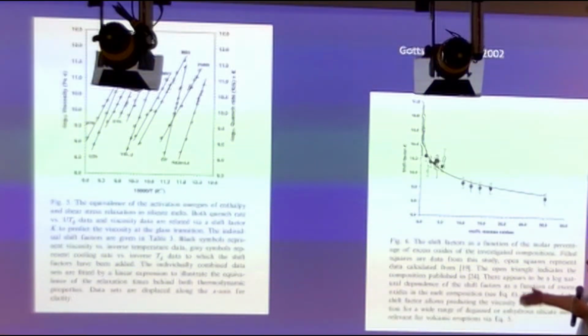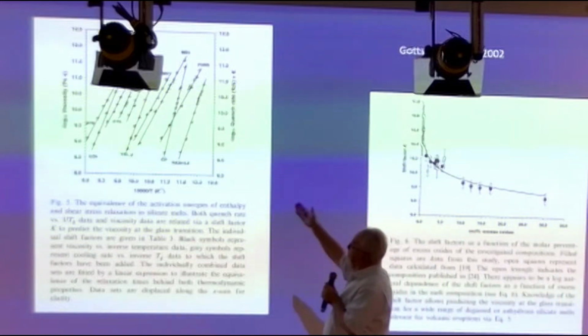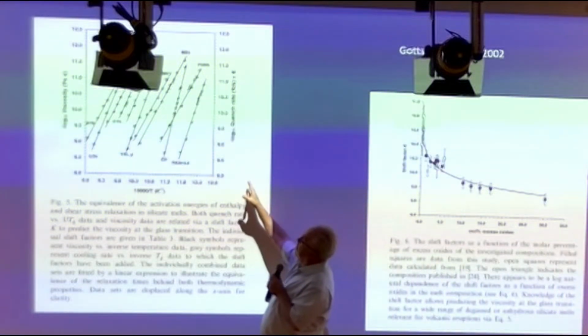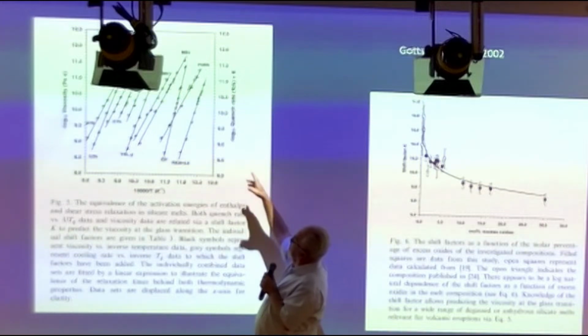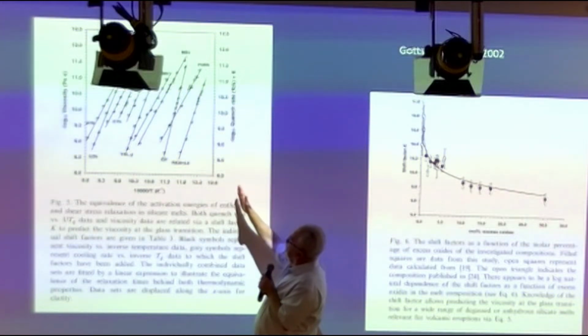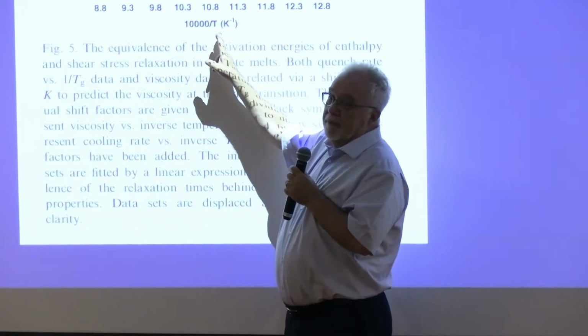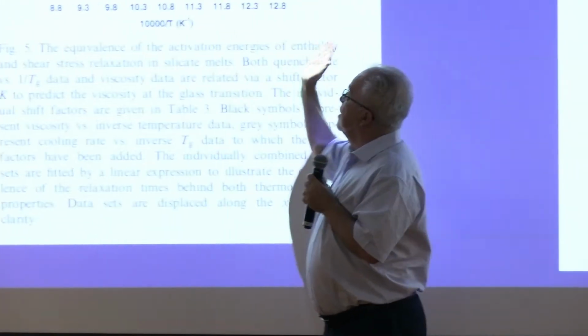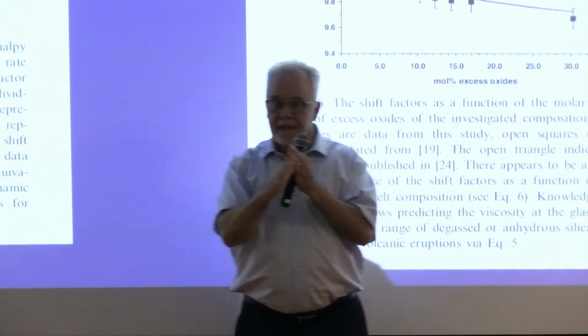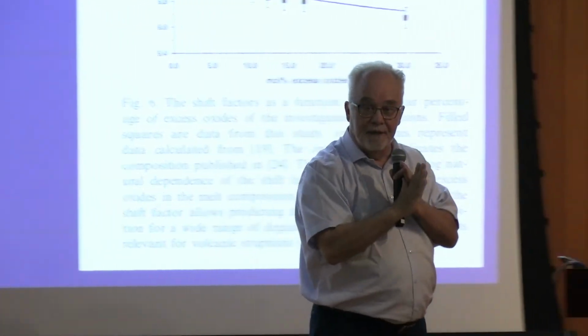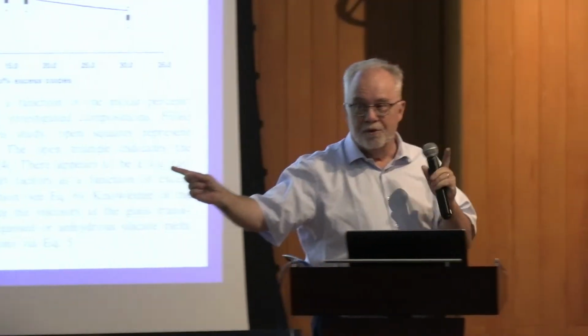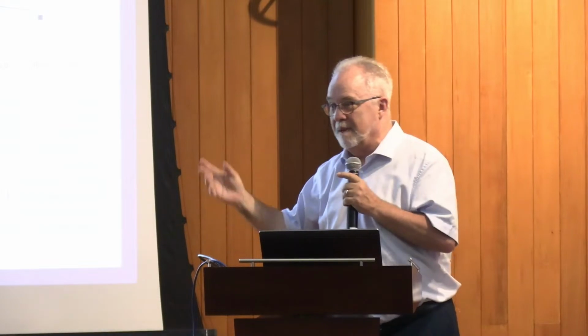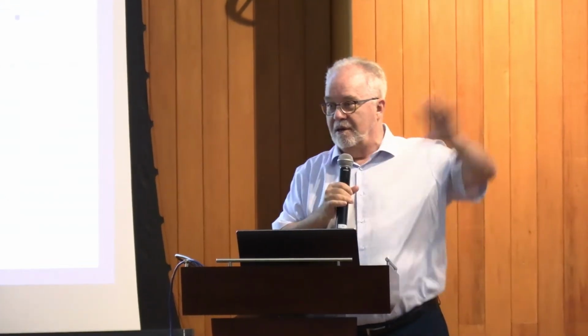And there you have them brought together. You have the two plots together, right? So you have the log of the cooling rate versus the peak temperature, and then you have the viscosity versus the temperature of measurement of viscosity. And you see that the two colors of symbols, they all fall together on that plot. So this is absolutely a very fundamental observation using two very different machines. Normally in the past, people who worked in viscometry labs would never talk to a calorimetry person, right?